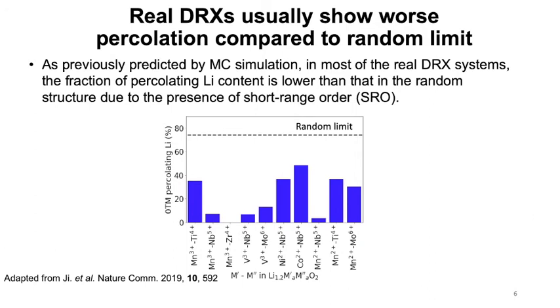And extensive Monte Carlo simulation on various different chemical spaces, shown here in this figure, actually demonstrates that most of the short-range order is actually harmful, because here is the theoretical value of percolating lithium if we assume the structure is completely random, or there is no such short-range order. It can achieve almost 80% of lithium that is connected to the 0TM network.